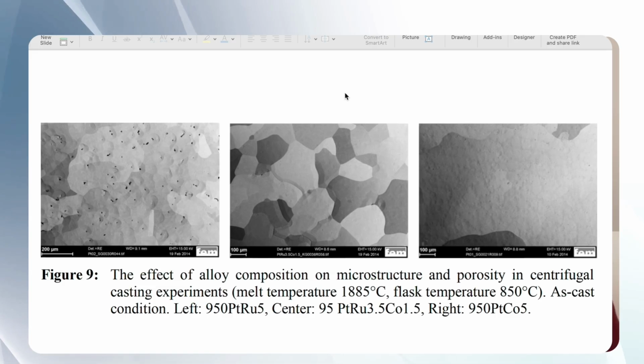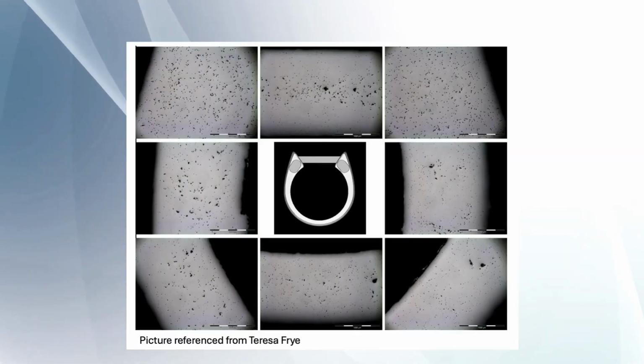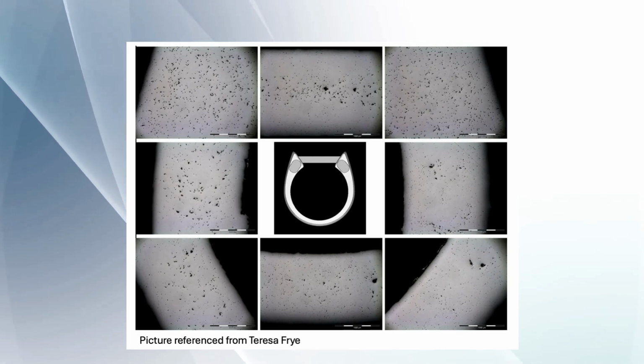What we see on the left are these dark spots. This is the microporosity that everybody fears when casting platinum ruthenium. Because when you polish the alloy, this porosity shows up, and it's like a little web. It's almost like a surface roughness, but they're actually microporosities.